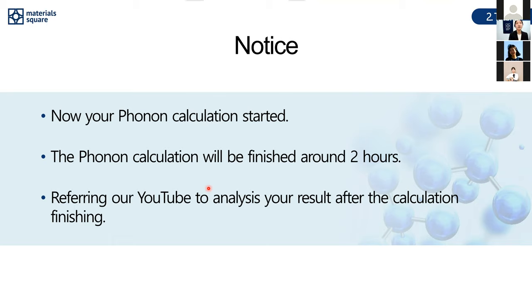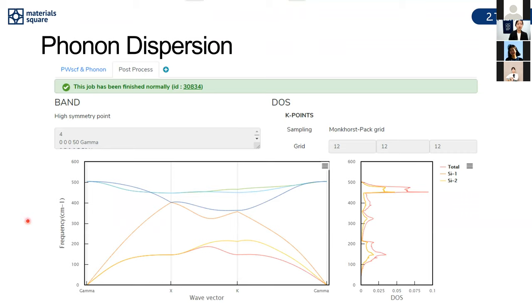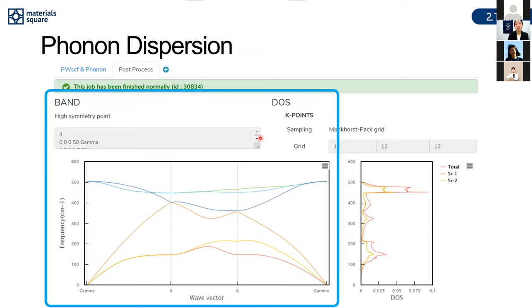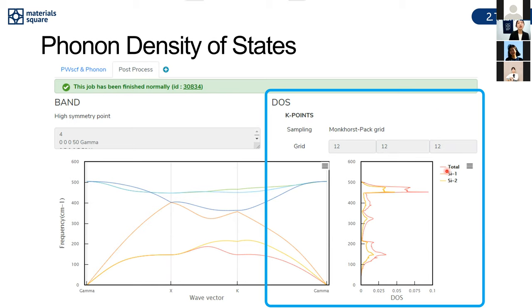I'll now show you the calculation results in the tutorial presentation. From the phonon module you can obtain these properties. First, phonon dispersion: after the job finishes, you can see the phonon dispersion plot. The total number of branches depends on the number of atoms in the primitive unit cell. If the crystal structure is unstable, negative frequency values will appear. Second, phonon density of states shows the number of modes in each frequency range — if the DOS k-point grid is too small, the DOS graph shape will not be smooth and you should increase the number of k-points.